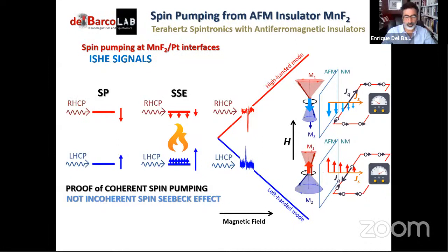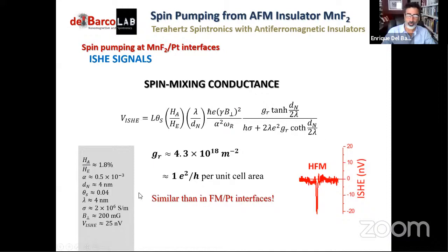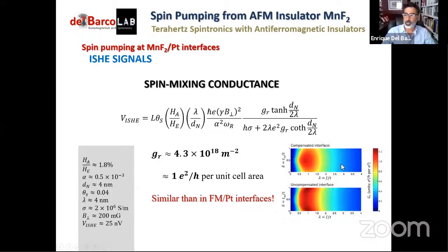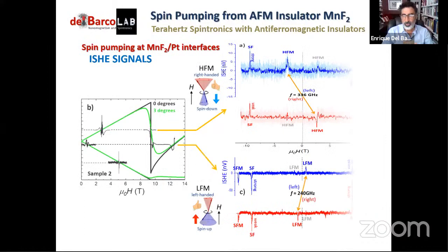The other thing we can do is to look at the magnitude. We know what the power of the microwaves we're using is at the sample position. And then we can estimate the mixing conductance. And we find it very, very close to the universal quantum conductance that was actually expected from theory, which is actually very nice.